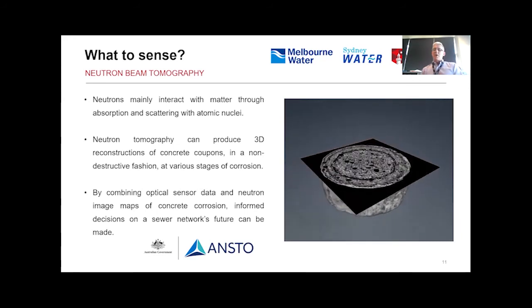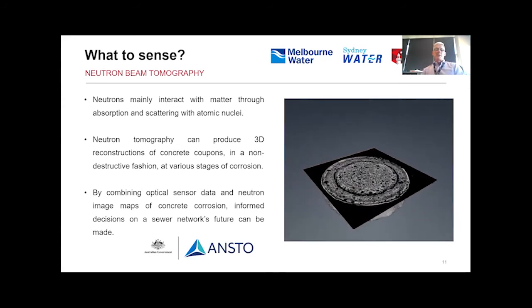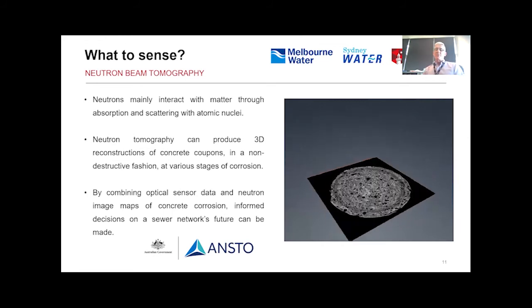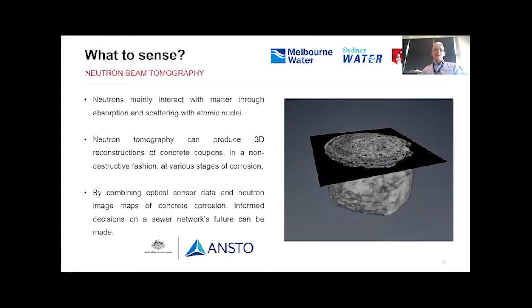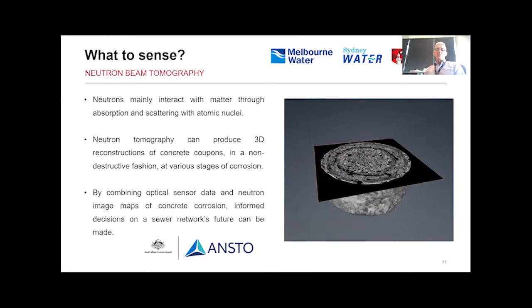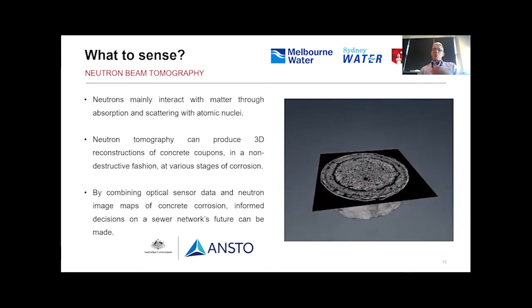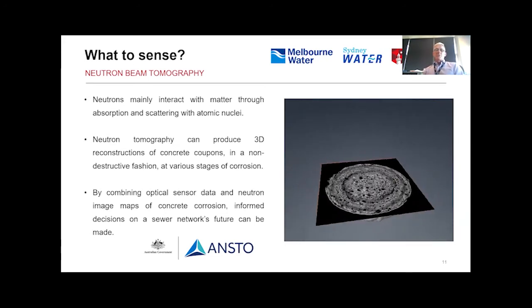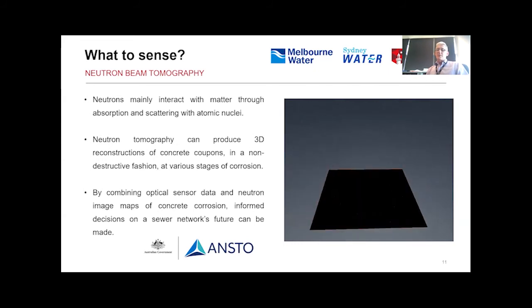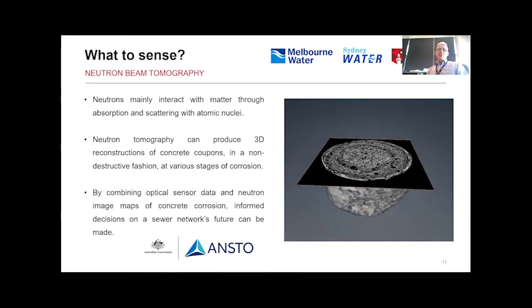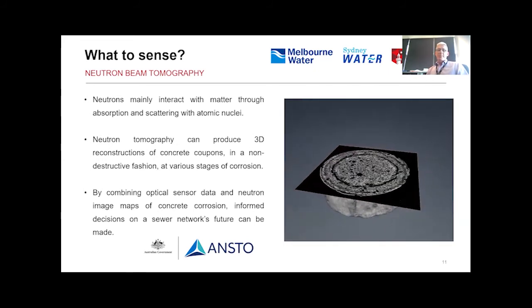And that's actually an iron ring, which tells us there's species migration that happens inside the concrete during this corrosion process. So it's these sorts of tests that give useful insights into how the corrosion front moves through the concrete, and indeed, what are the sorts of things we need to test that tells Sydney Water and others that they actually have a problem.